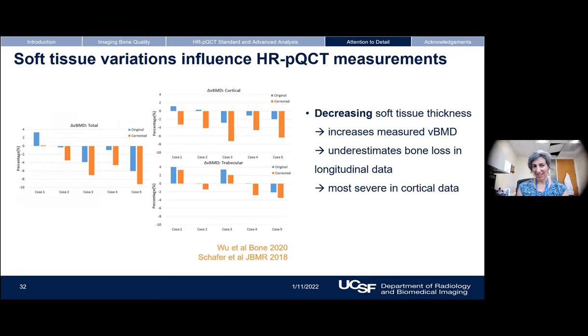And then we applied a correction factor from those phantom data to real data that we acquired in bariatric surgery patients. And that's what you're seeing here. So cases 1 through 5 are 5 individuals who underwent bariatric surgery. In blue, we have the original changes in volumetric BMD, total, cortical, trabecular. And then we applied a correction factor based on the artifact that we know occurs just due to change in soft tissue alone. And that's what you see in orange. And so what we found is that the decrease in soft tissue thickness underestimates bone loss in longitudinal data. And again, this is most severe in cortical data.